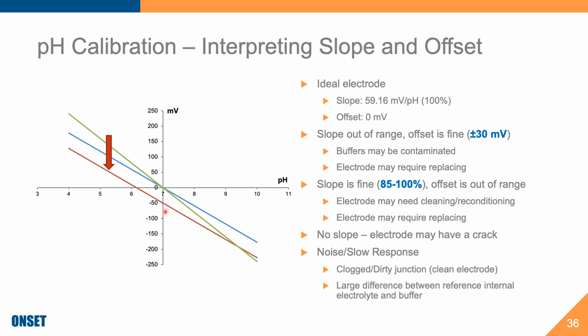If you don't have a slope, it's possible that your electrode's cracked enough that it's not able to read a different potential. It's reading the same thing no matter what solution you put it into. That may be a crack on your electrode, and it is possible to have micro cracks that you can't even see on your electrode. So be aware of that as well.